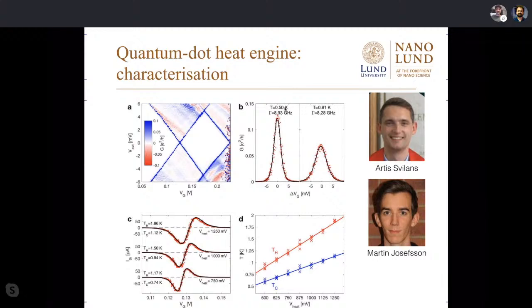From these data, we can also extract the coupling strength of the quantum dot to the baths. So we are assuming symmetric barriers and then can get a gamma of the tunnel coupling to the baths. This is done at two different temperatures, and the fact that you get similar gammas for two different temperatures is one nice confirmation. Then on the bottom left here, you already have thermoelectric measurements.